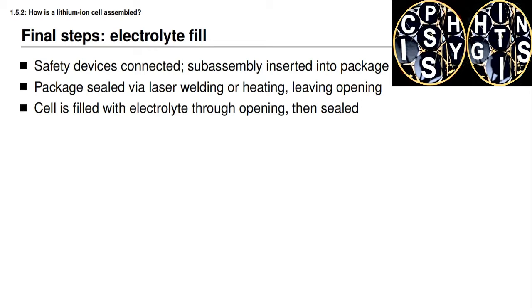electrolyte. It's interesting that even at this point, the cell may not be completely wet with the electrolyte material, and it may take several charge-discharge cycles for that to happen. And so it's not uncommon to see the first several cycles of a brand new lithium-ion cell appear to increase in capacity as this electrolyte makes its way into all of the pores and then allows the lithium ions to flow to all of the solid active material. And then after these initial cycles where the capacity appears to be going up, then it starts to go down as this cell ages. In any case, after we have filled the cell with as much electrolyte as we're able to, we seal the remaining opening using, for example, a laser weld or some kind of a heating process.